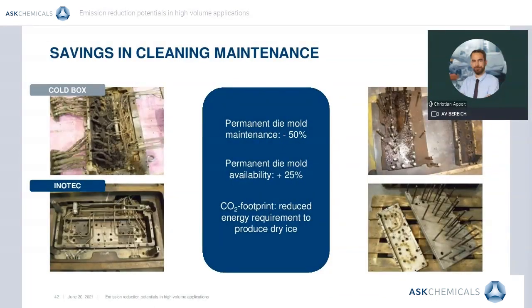Besides the ecological benefit of missing emissions in the casting process with Inotec, savings in cleaning maintenance for the permanent die mold are a result as well. When casting with organic sand cores, the buildup of condensates occurs at the permanent die mold, which must be removed by employees in regular intervals to ensure correct functionality, especially of movable parts. The physical strain for employees involved in this work is high. In addition, there is a very high level of noise pollution.